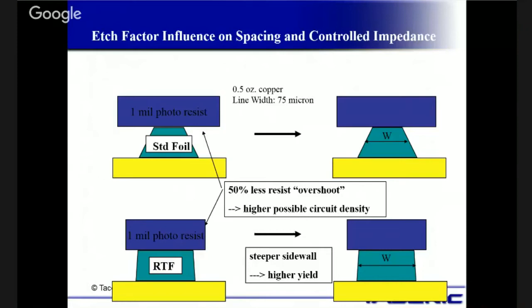And so I always ask people, when you're doing a microwave board, what's the distance between this trace and that trace? And how do you measure that? It's very, very difficult, because you measure the foot, you measure the top, but it affects the coupling on a board. Whereas the reverse treated foils, which are smoother, etch very, very straight sidewalls. And to me, it's a lot easier to figure out this distance, and it's always consistent. Whereas this always changes, because it depends on how much time it takes to etch through that skin when you're etching the boards.